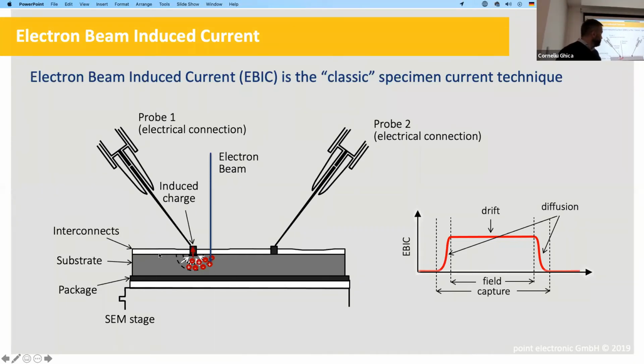So as we scan the beam from left to right in our example, where we're very far away from the electric field, we will get no signal because the electron hole pairs will recombine. As we come closer to the field, some of the electron hole pairs will diffuse, will walk randomly, and some of them will get collected. And the closer we are to the electric field, the more we collect. So there will be an increasing edge. When we are inside the field, the majority of the electron hole pairs will be collected, and we have a high current, and then we go through the other side. So we get this kind of profile where we have high current where there is a field, and we have quite diffused edges around it.